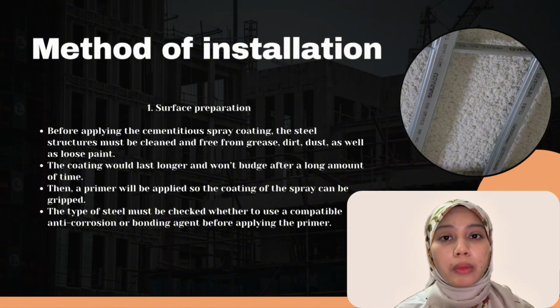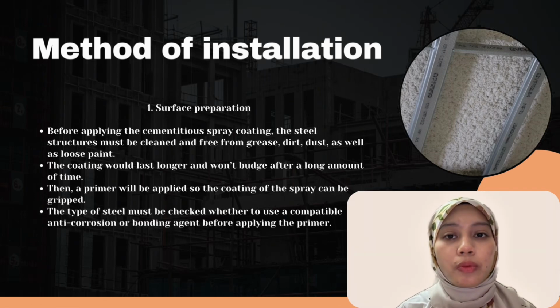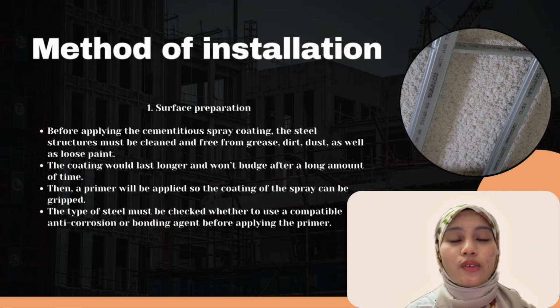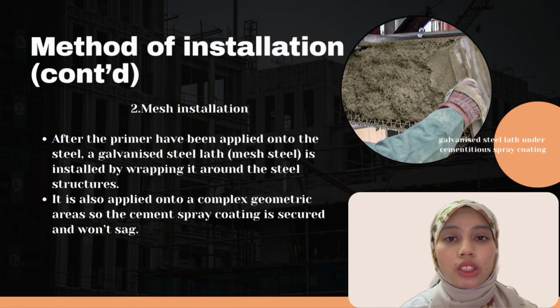Now we will look at the method of installation of cementitious spray coating for steel connections. The first step is to prepare the surface of the steel connections. The surface of the steel connection must be free from grease, dirt, rust, and loose paint. Then, a primer will be applied on the steel connection to help the cementitious spray coating bond. However, the type of steel must be checked to decide whether to use a compatible anti-corrosion primer or a bonding agent before applying the primer. The next step is mesh installation.